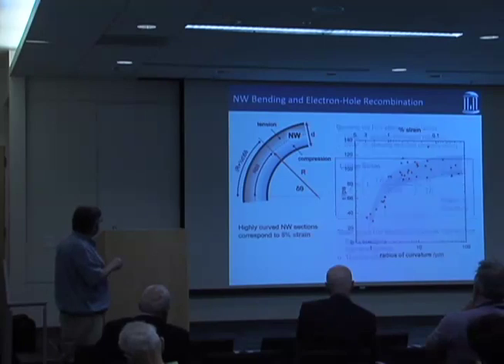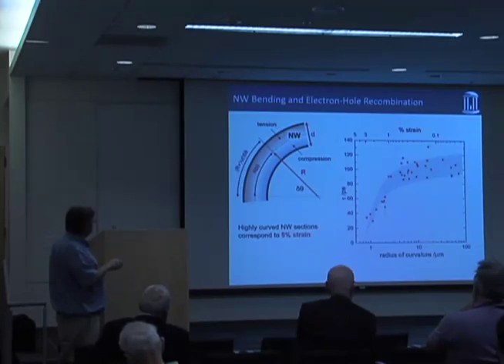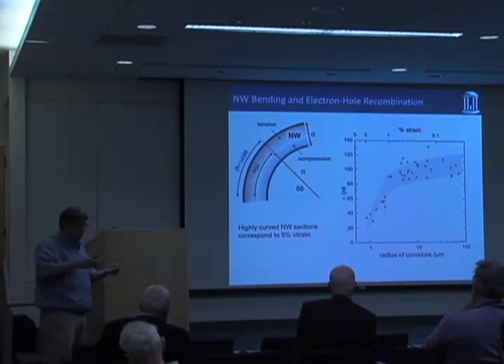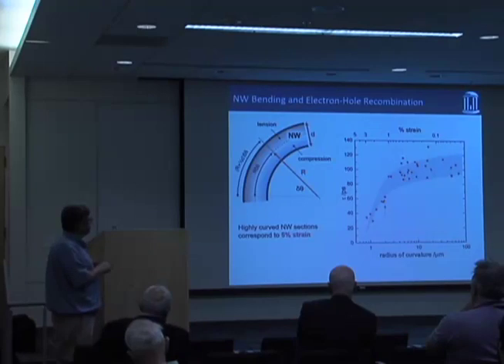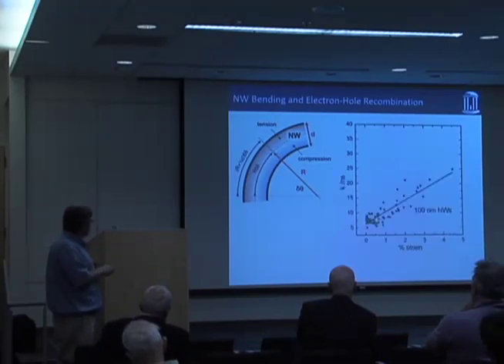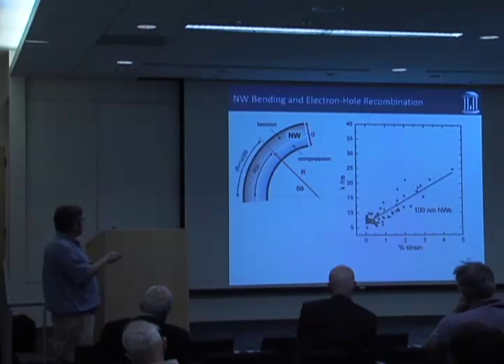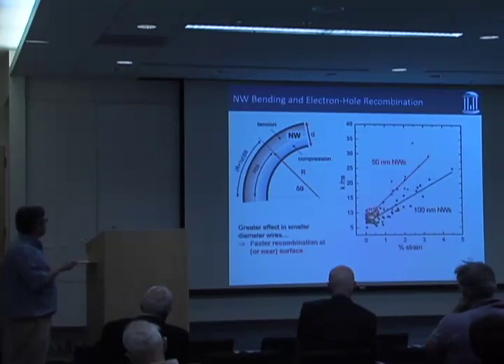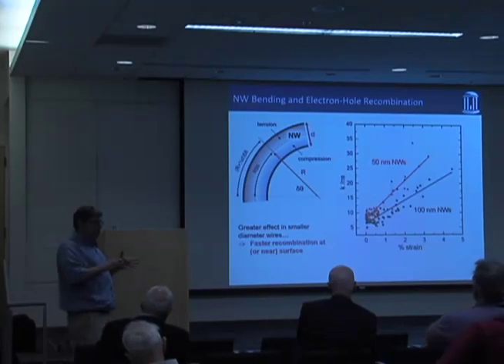And so now I can put a strain axis up here. At the most bent we had, at least in this data set, we were somewhere around 3 to 5% strain in the nanowire. This is more or less the same data, but now it's the rate of recombination, on a linear scale here. This is with 100 nanometer wires. If you do it with 50 nanometer wires, it's a little bit different, which told us that whatever was going on was happening either at or near the surfaces.